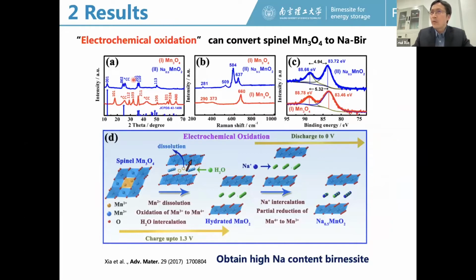So in one of our previous works, we used electrochemical oxidation, which can convert the spinel Mn3O4 to sodium Birnessite. And by using this method, we can obtain a high sodium content Birnessite, which has a sodium to manganese ratio of about 0.5.